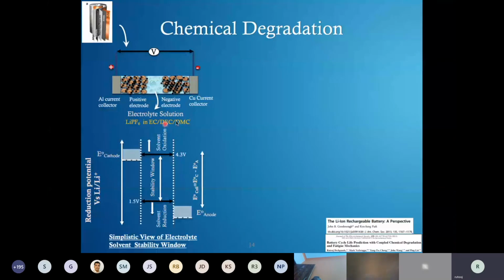Now the problem is all of these carbonates, or any solvent for that matter, have a particular stability window. So they are stable in a particular voltage window. For example, these carbonates are stable between 1.5 to 4.3 volts at room temperature at storage conditions. The problem is our negative electrode has a potential of less than 1.5. It has an average potential of 0.85 volts, whereas the positive electrode has a potential anywhere from 3 volts to 4.3 volts. So basically, the electrolytes are not at all stable on the negative electrode surface, and in some cases they are not stable on the positive electrode surface as well.